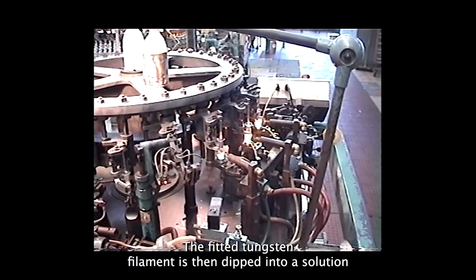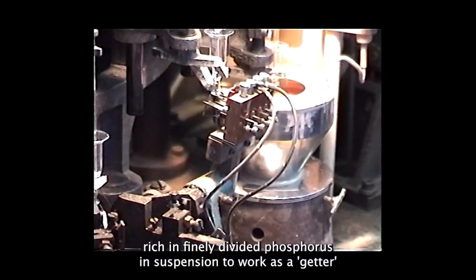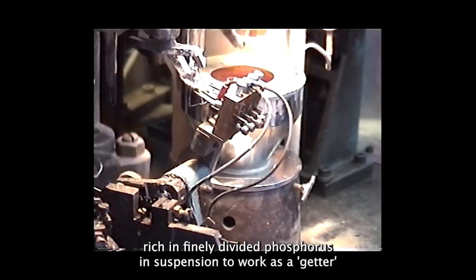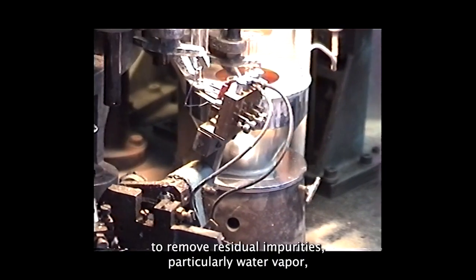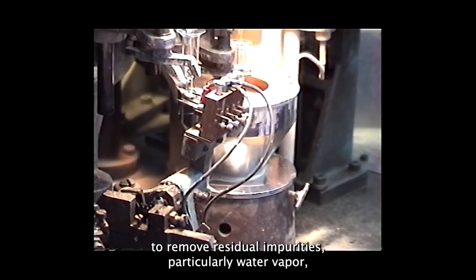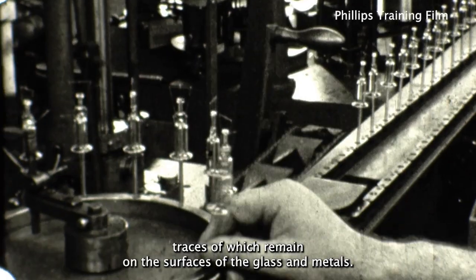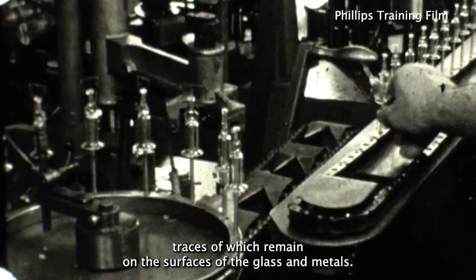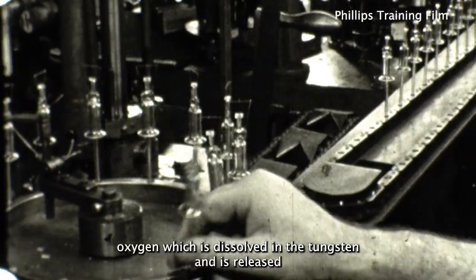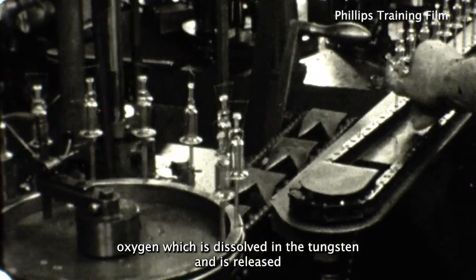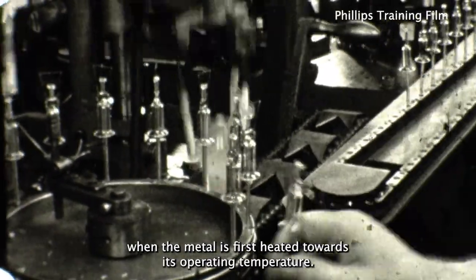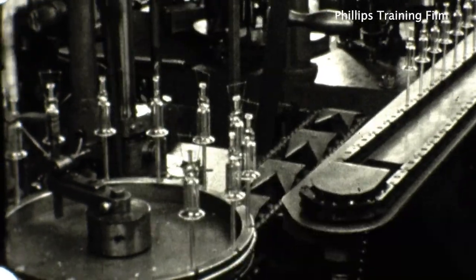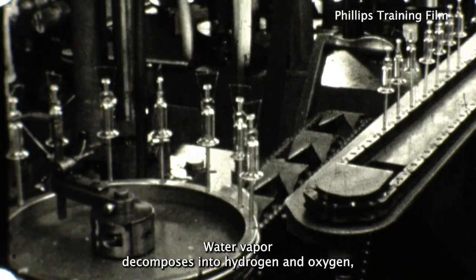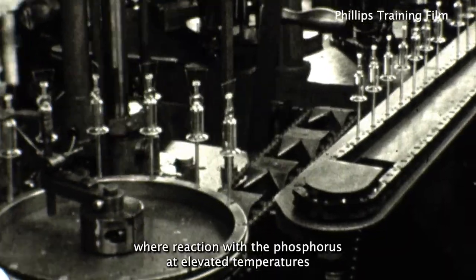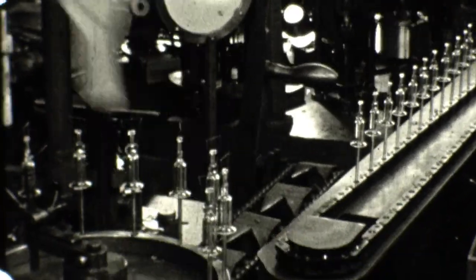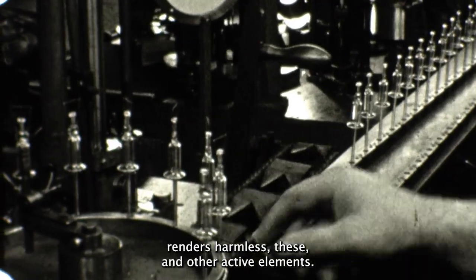The fitted tungsten filament is then dipped into a solution rich in finely divided phosphorus in suspension to work as a getter, to remove residual impurities, particularly water vapour, traces of which remain on the surfaces of the glass and metals. This also includes oxygen, which is dissolved in the tungsten and is released when the metal is first heated towards its operating temperature. Water vapour decomposes into hydrogen and oxygen, where reaction with the phosphorus at elevated temperatures renders harmless these and other active elements.